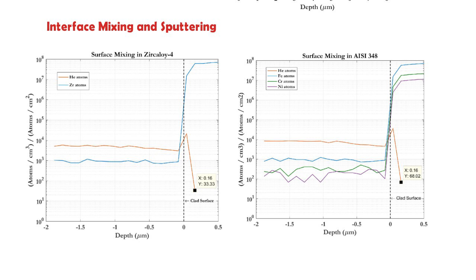Also, some of the clad atoms are removed by the recoil atoms that come back out of the clad. This is known as sputtering. However, less than 1 atom was found to sputter per ion, which is not significant.